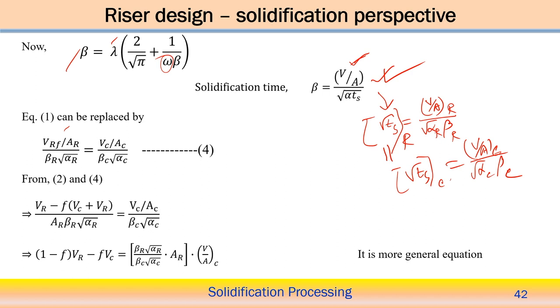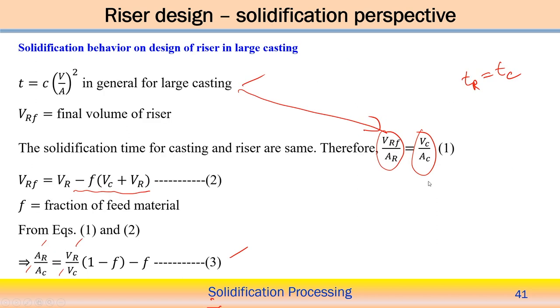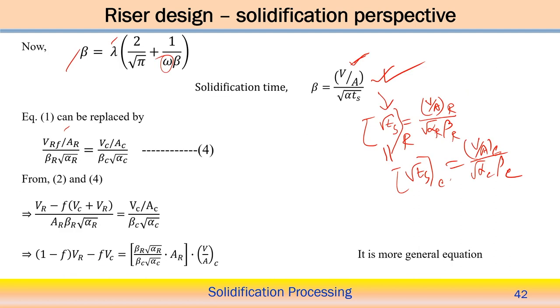Now combining equation 2 and 4, we have already estimated in equation 2 the VRF in terms of the other parameters VC and VR, such that we replace the final volume of the riser in terms of VC and VR, because VR is the initial volume of the riser. So it is easier to calculate with VRF replaced by f into VC plus VR. From equation 2 we put it here, and we can do this rearrangement of the different terms. So AR and AC are here, beta R square root and so on. So we can do further rearrangement, 1 minus f into VR, and make it common from here.